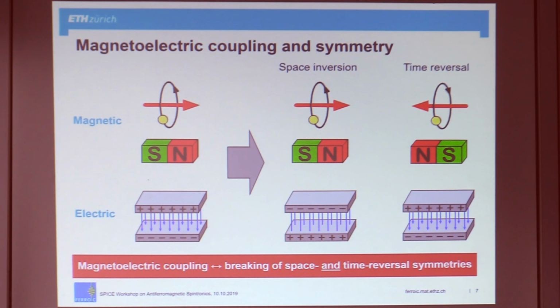Such a static capacitance, however, is left untouched. So this is a symmetry operation for electric field phenomena. So putting that together, if you want magnetoelectric coupling effects, you involve magnetic fields, you involve electric fields. So that can happen if both time reversal symmetry and spatial inversion symmetry are broken.